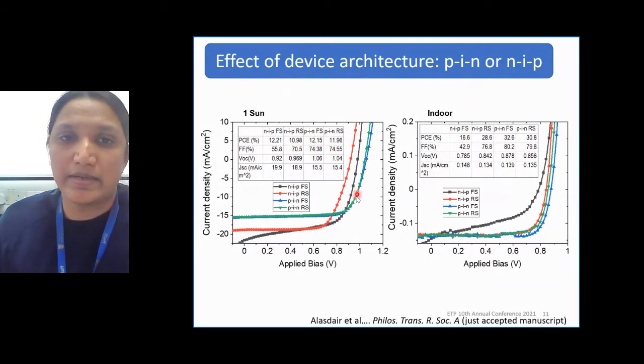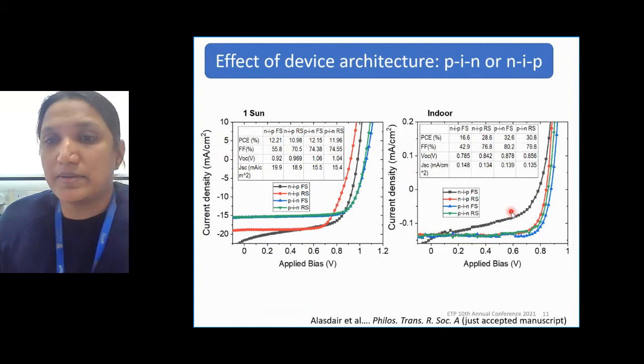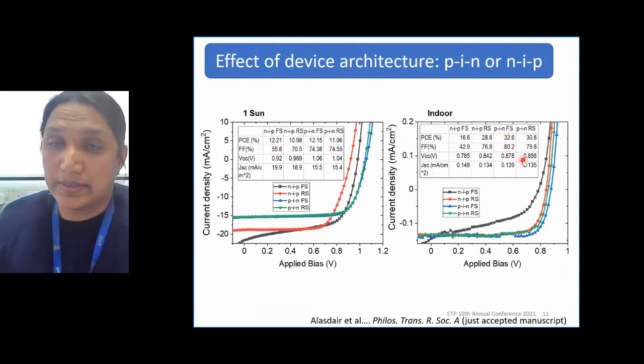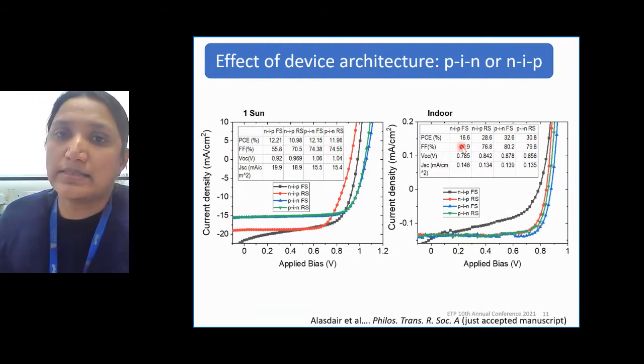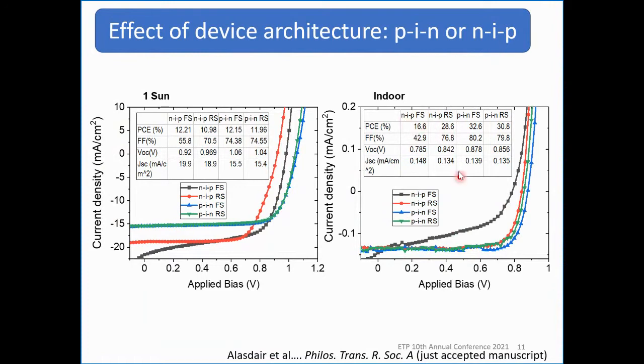But we can see that the PIN device structure has no hysteresis or very little hysteresis compared to NIP. NIP devices show higher hysteresis. When we come to the indoor application, the indoor JV curves, we can see PIN devices show a high power conversion efficiency of more than 30%, and it is the same for both forward and reverse scans, with a small hysteresis effect. Whereas in the case of NIP devices, we see a large deviation in the efficiency obtained for forward scan and reverse scan. That means these NIP devices show a higher hysteresis effect. Also, if we compare both one sun and indoor JV curves, we can see that the PIN devices consistently show less hysteresis effect and high power conversion efficiency, whereas NIP devices show hysteresis and it gets enhanced under the indoor illumination.